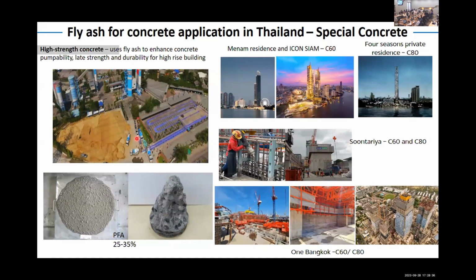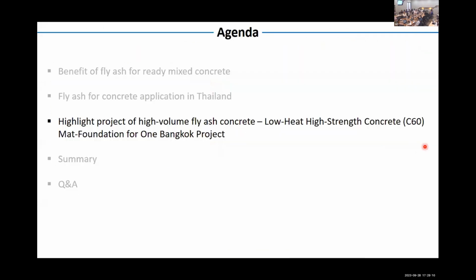And we once tried to make a pump simulation for the concrete. You can see the pump line here. The distance of the pump line here is about 600 meters. We pump the concrete in and we observe the concrete come out with no problem when we use fly ash like this. So there are many applications in Thailand where we use fly ash so far. Right now we generally use it for C80 high strength concrete in Thailand. Okay, this is some background of applications in Thailand for using fly ash.